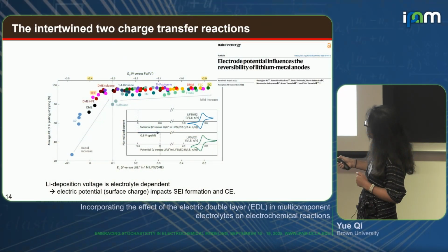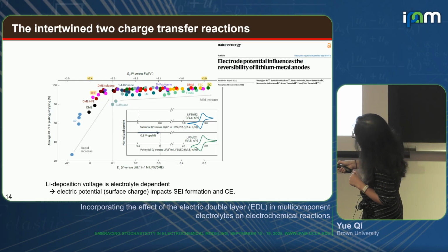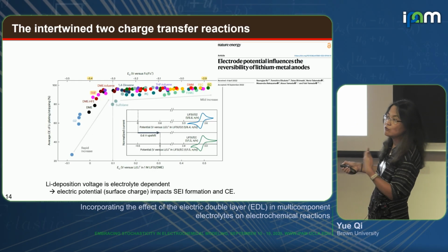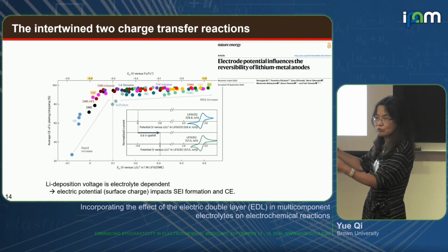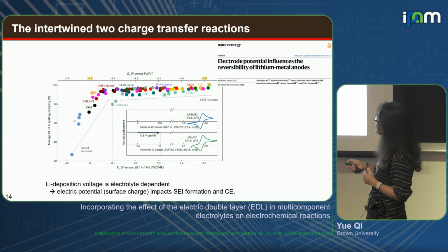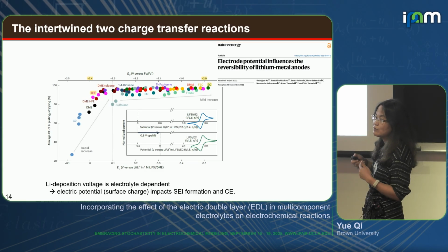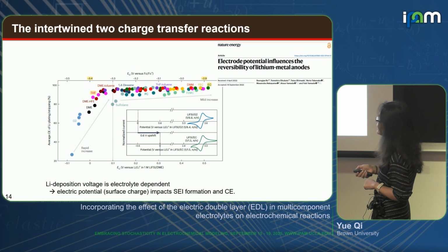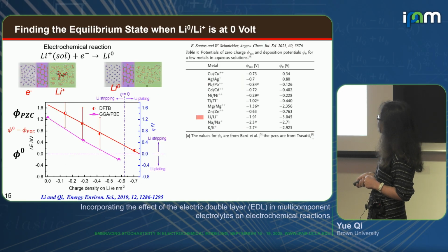It's true that you can see that the measured reduction voltage for lithium deposition really changes in different electrolytes. If you see the same color, it's the same electrolyte at different concentrations. And this is their Coulombic efficiency, CE, which is related to the energy loss, the electrons you lost to react with electrolyte. So the two things are competing. So we have to find a common reference to study all these competing reactions. So that's thermodynamics. And we did actually need to come up with the kinetics.